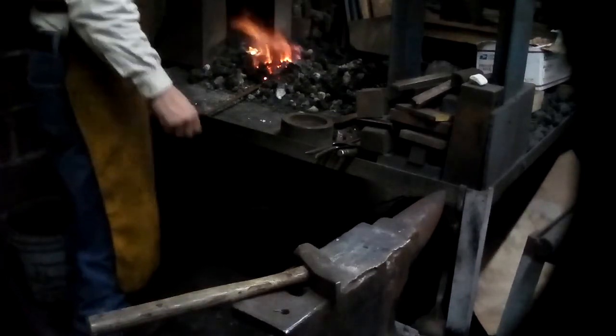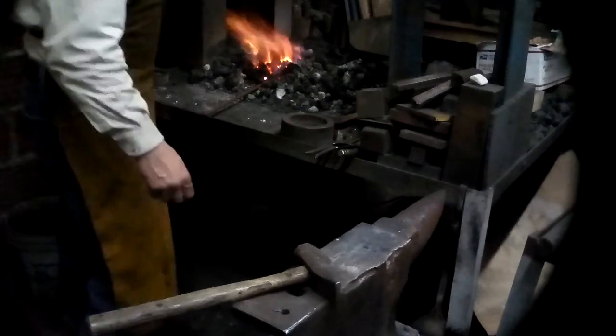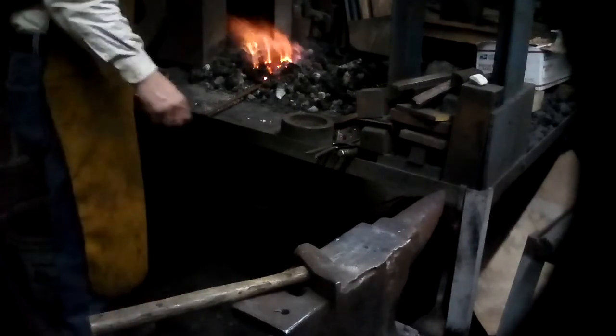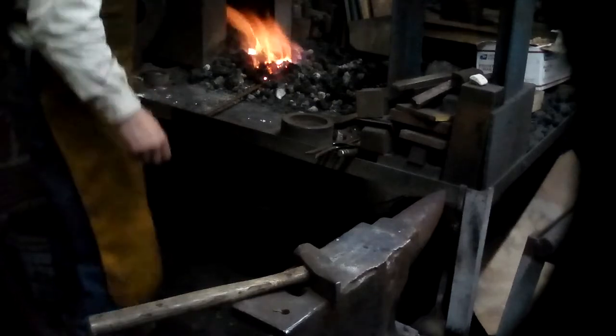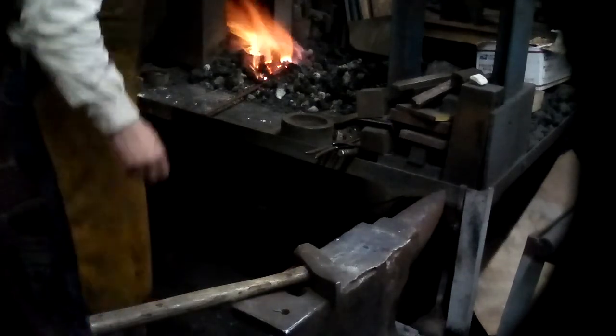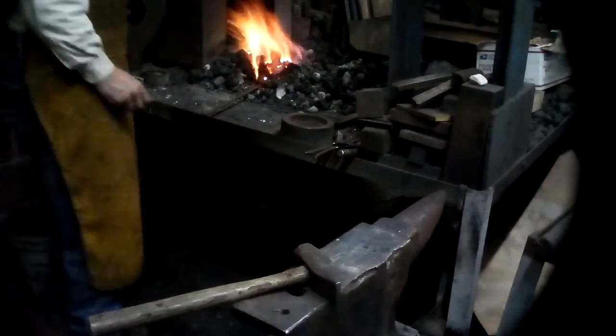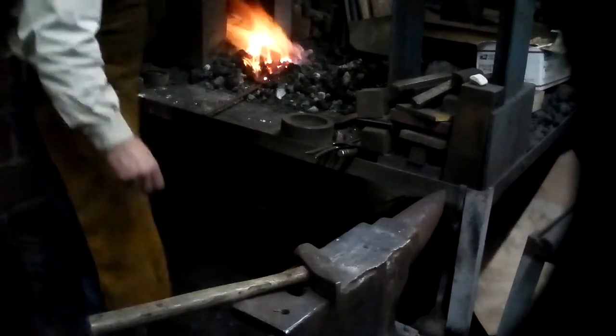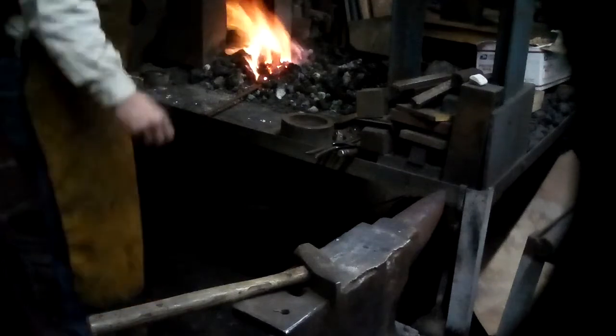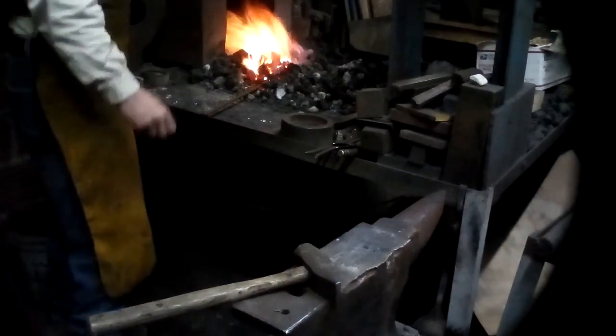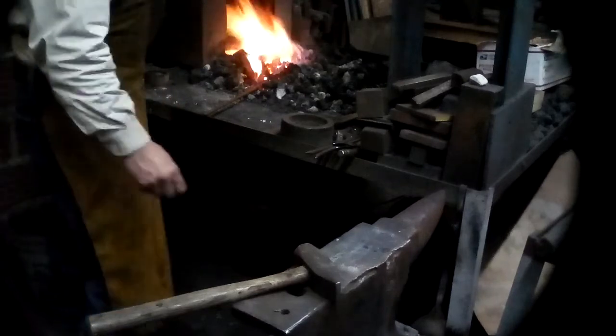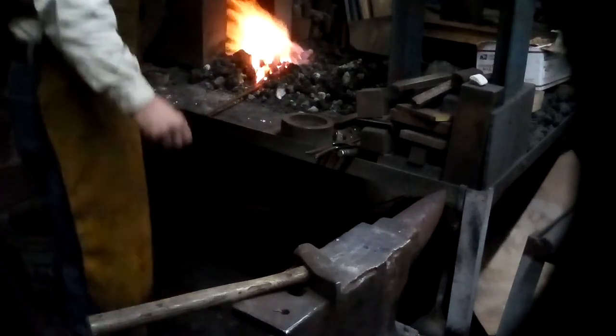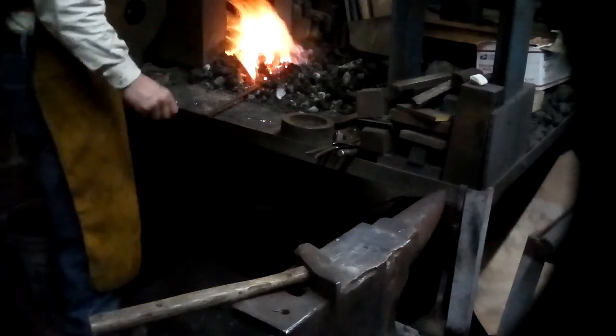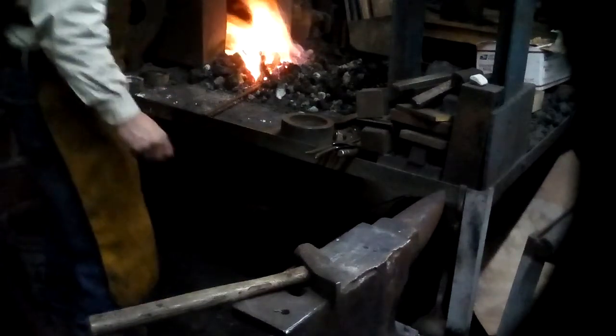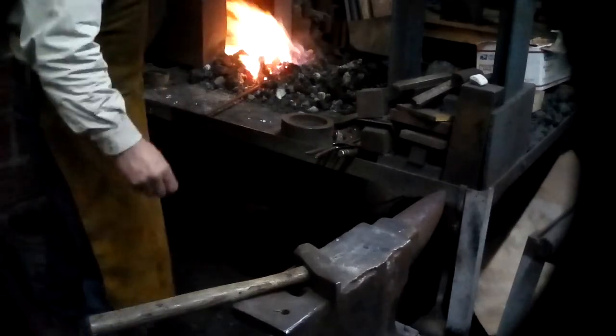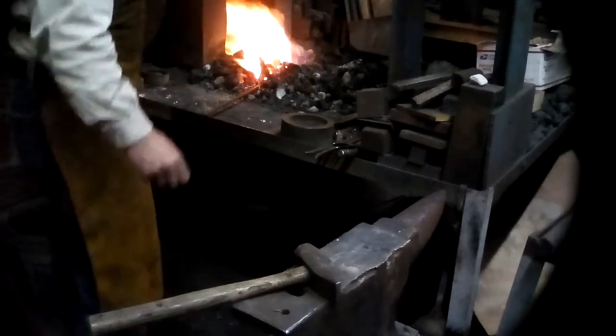You can think of it as that the more carbon there is in steel, the lower the melting point. So the forge welding range is generally at least 100 degrees below the melting point. So things like wrought iron, you can weld at a bright yellow heat at maybe 2,500, 2,600 degrees. Mild steel is maybe 2,400, 2,500 degrees on the upper range. But high carbon steel, like files and tool steels, can weld at temperatures around 2,100, 2,000 degrees.